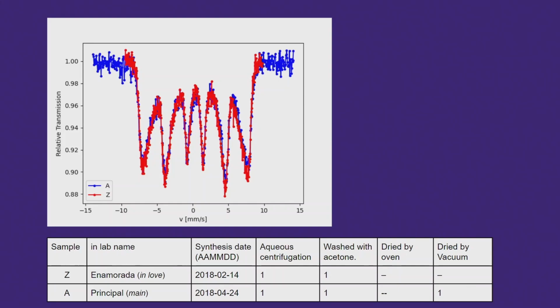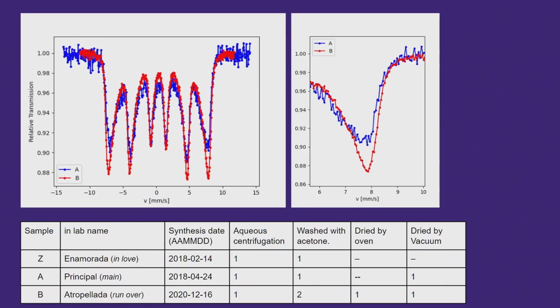Here we have the first synthesis that was done. There was some problem at the end, and we didn't have nanoparticles to use in the biological experiments, so we made another synthesis, the same synthesis, and we saw by Mossbauer spectroscopy that there was a very good coincidence between both nanoparticles. So all the first biological experiments, the only ones we have at the moment, were done with this synthesis. But it started to run out, and we needed another one. And that was what happened.